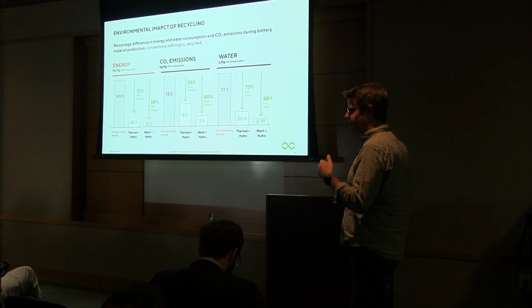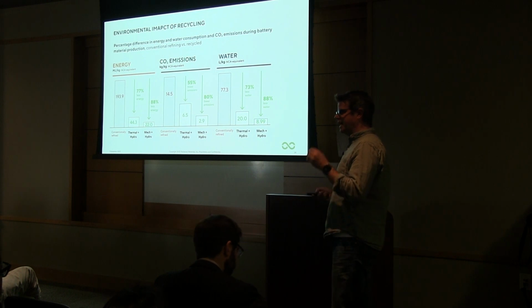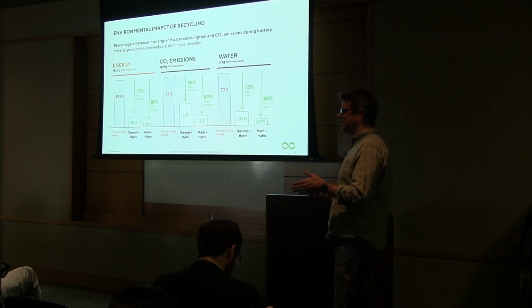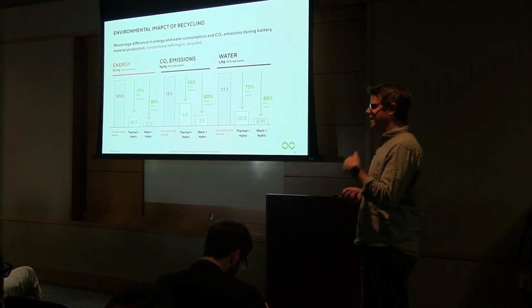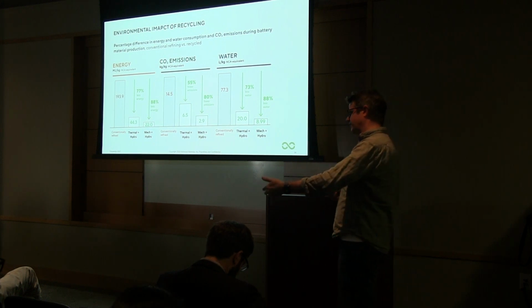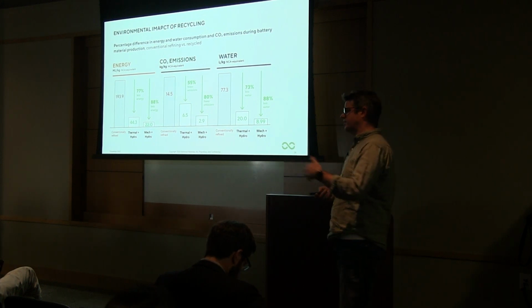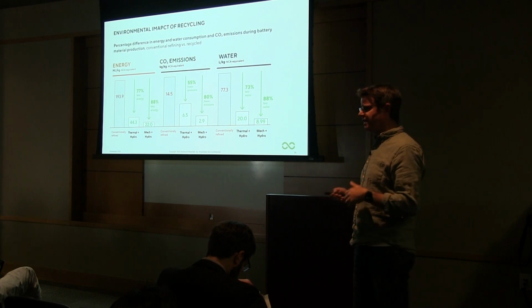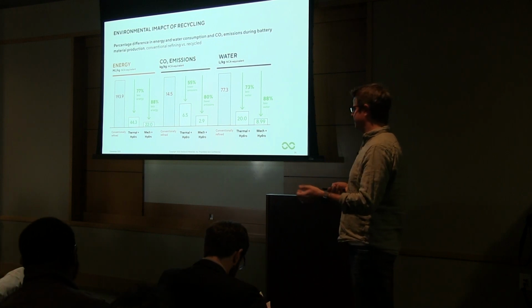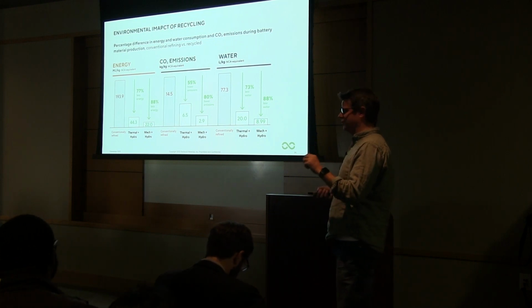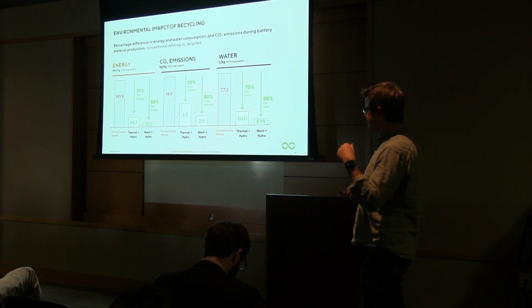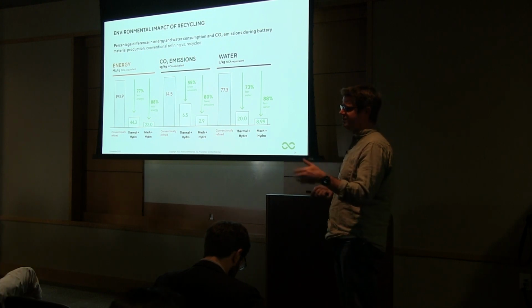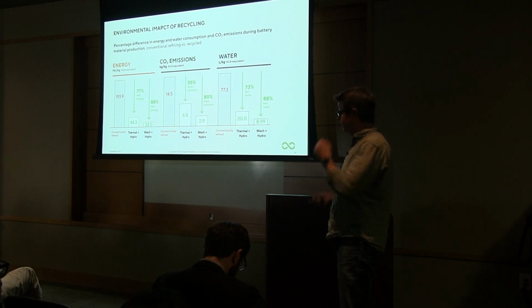And a lot of that has to do with the reagents that we use and the processing steps that we use as well. So it's not actually about thermal processes, because in our thermal processes we're not combusting the graphite. It's not about combusting separator plastic. It's actually the CO2 footprint of the reagents that you're using, and the reagents are really defined by how you set your flow sheet up.